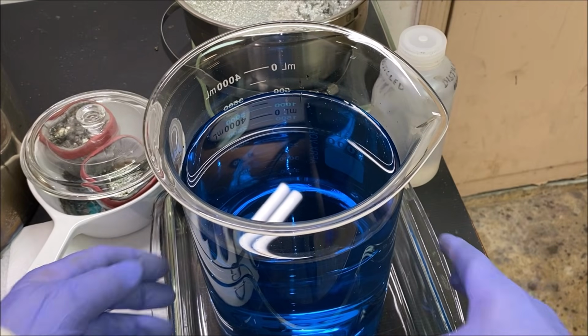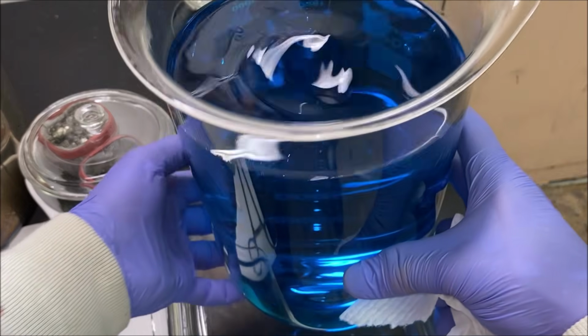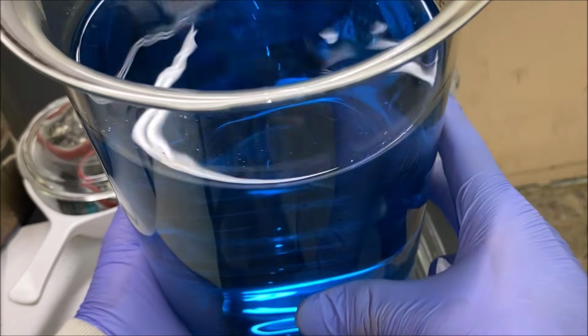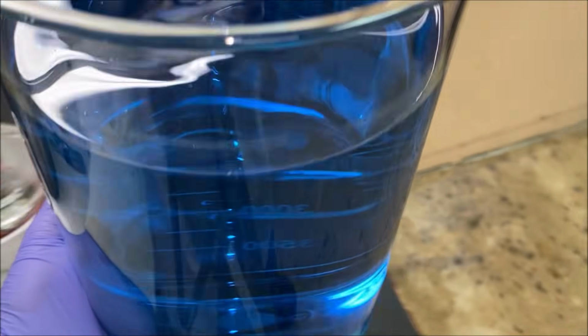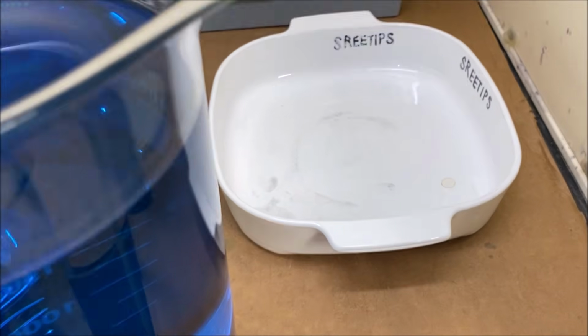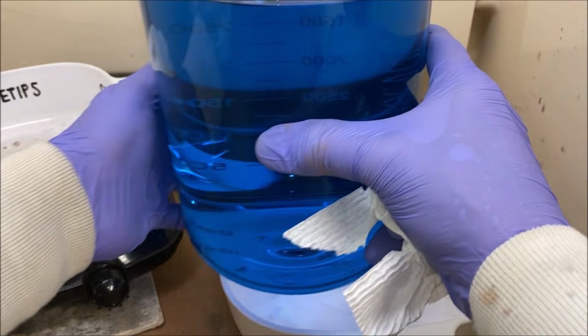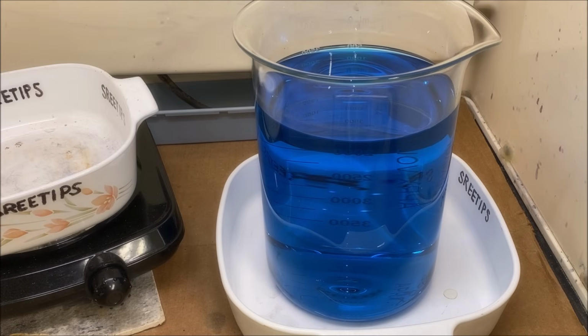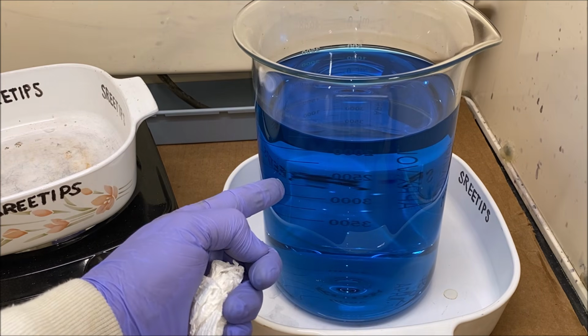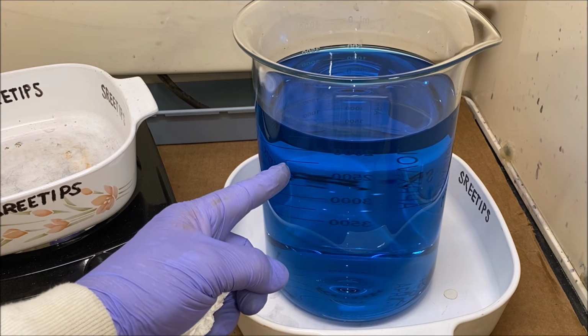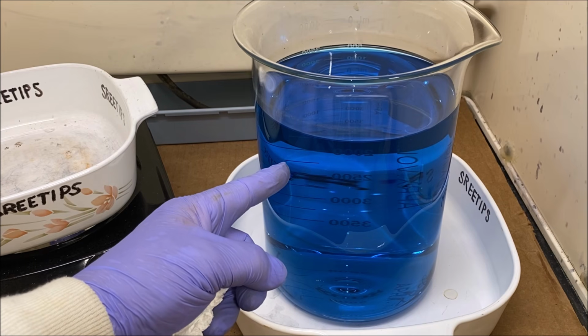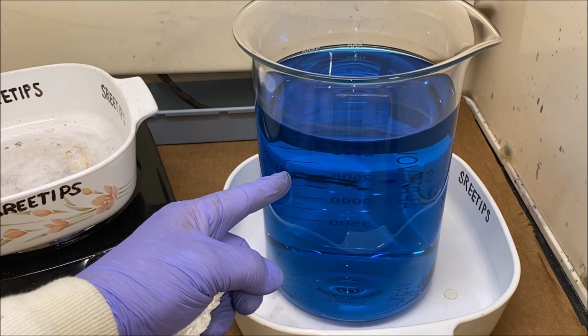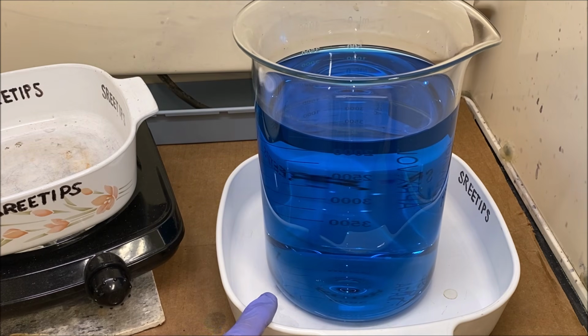This blue liquid is our used silver nitrate electrolyte. I've used it for 2 runs of the silver cell. And so now what we're going to do, carefully bring this over here to the fume hood. I never use the electrolyte for more than 2 runs of the silver cell because copper does build up in here. That's why the color is blue. From the dissolved copper, it stays in solution while the silver plates out on the cathode.